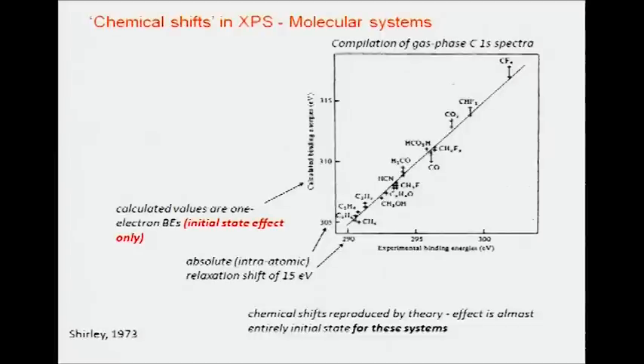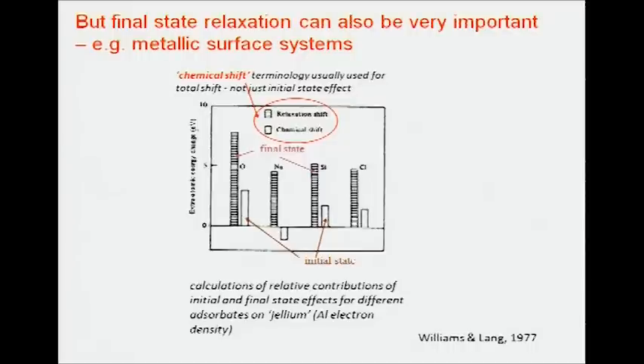But the idea that this initial state, this ground state, one electron binding energy, is the dominant source of the core level shift actually works quite well in some systems. So here's a compilation from Dave Shirley's group back in 1973 of the carbon 1s binding energy measured in this way for a whole series of different gas phase carbon-containing molecules, and you see there's a very nice straight line between the calculated energies and the experimental energies, although you also notice there's a shift of 15 electron volts, and that shift is due to this final state relaxation, the response of the electronic environment to the creation of the core hole. But in these systems at least, that final state relaxation appears to be much the same for all these different molecules. This is not, however, invariably true, and in the case of, for instance, adsorbates on metals, we certainly expect that to be rather different.